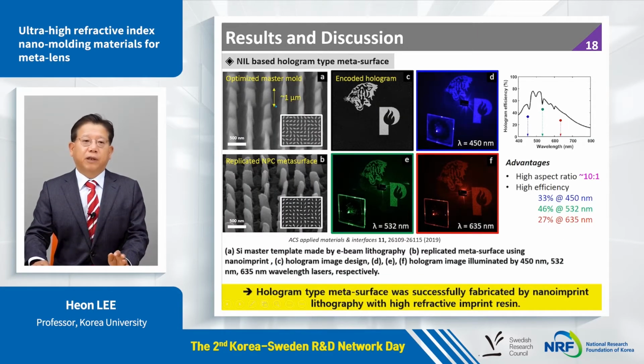This is another example. This is the optimized master mold, and this is the replicated nanoparticle composite metasurface. I mean, using this one as a master template, this one is imprinted. And this is an encoded hologram. The tiger head is the emblem of Korea University, and this one is the emblem of POSTECH. When applying 450, 532, and 635 nanometer light, it can create a very nice hologram image. So a hologram-type metasurface was successfully fabricated by imprint lithography using high refractive index imprint resin.